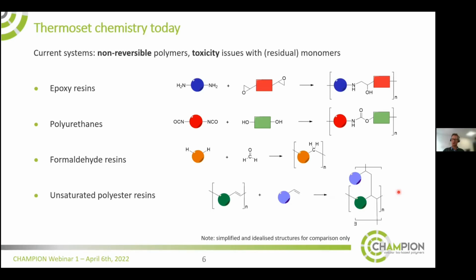Most of these thermoset chemistries are non-reversible chemistries, meaning you can't reverse the materials back into monomers. And secondly, and importantly, many of these chemistries use toxic chemicals, for instance, based on bisphenol A, on isocyanates, or by using formaldehyde. And styrene is also hazardous.